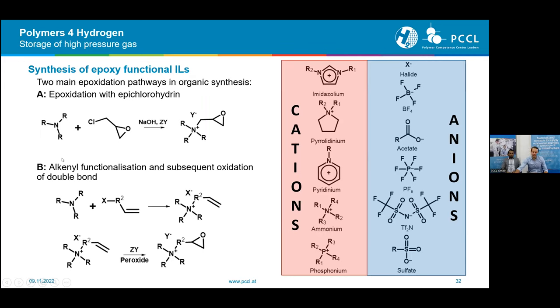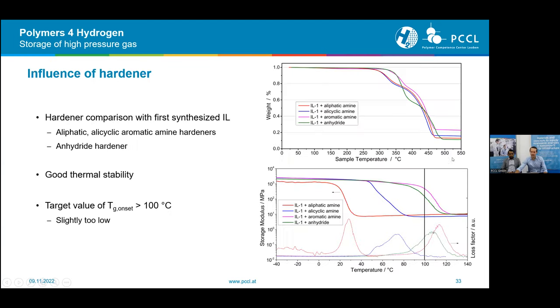This would be the easiest step. The second pathway is to functionalize it with double bonds. And afterwards, you can oxidize those double bonds to epoxy groups, and then exchange the anion. This gives you a lot of freedom in terms of the chemical structure, and also does not include this very toxic epichlorohydrin. On the right, you can see examples of cations and anions, and with all those combinations, there is a really vast diversity in what chemical structures you could use.